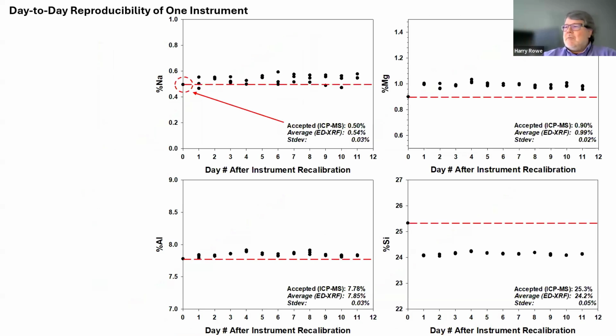The thing to look at is day-to-day reproducibility. I don't see this plotted by a lot of other folks, but this value here, 0.5% sodium, is the ICP-MS value for one of my references. And we run this reference on every instrument, everywhere on the planet that we have an instrument, every day before we start. And this is the day-to-day reproducibility of it. Okay, we run it 3 times, right? And that average is 0.54. So I am 0.04% off with sodium, with a standard deviation of 0.03.